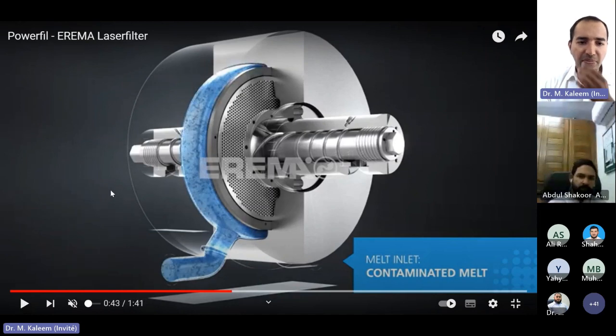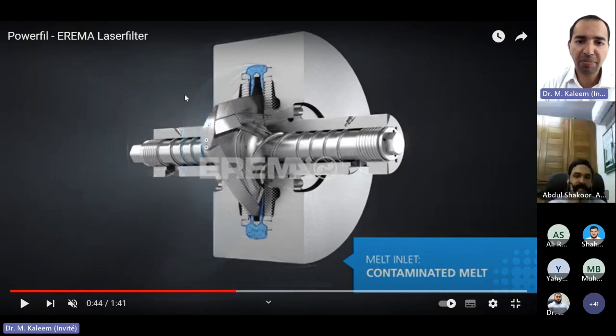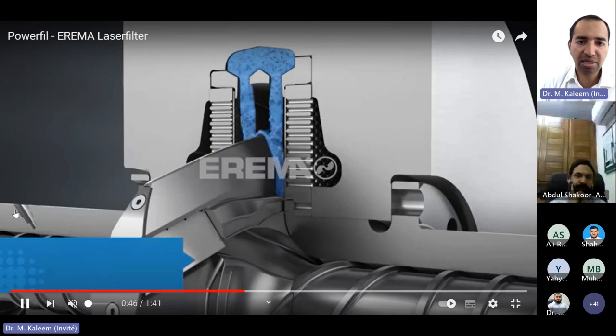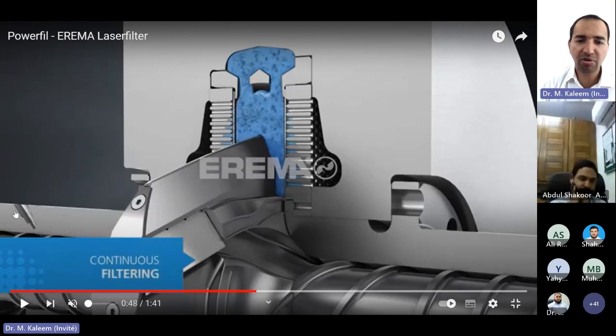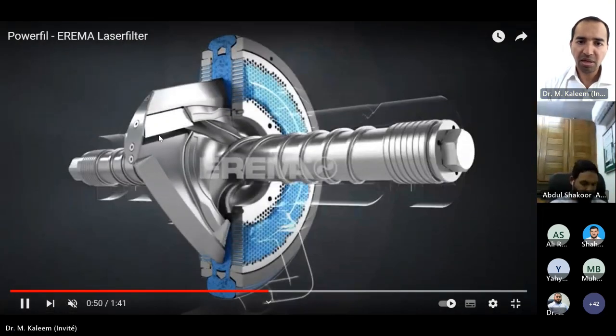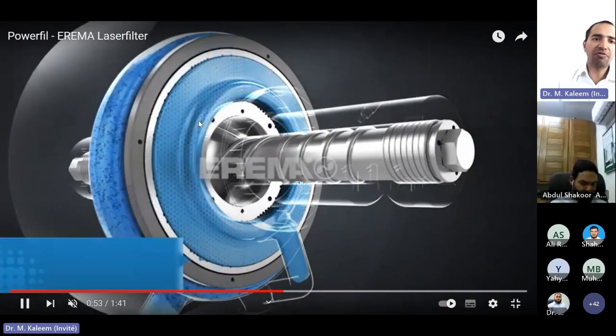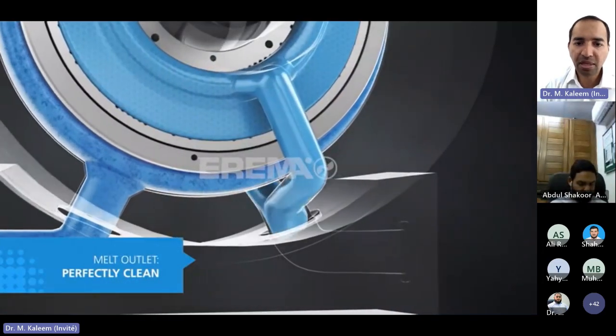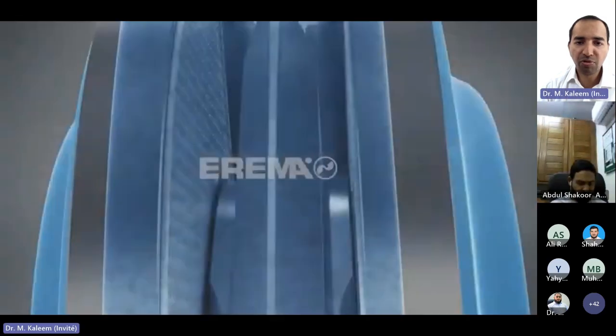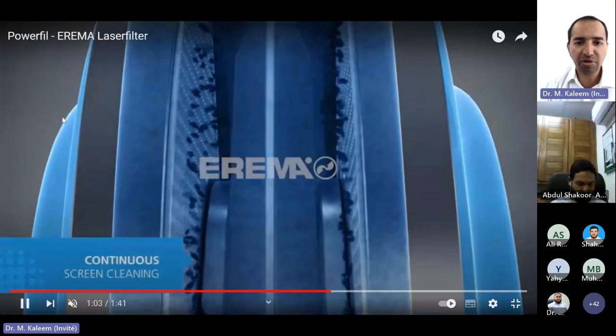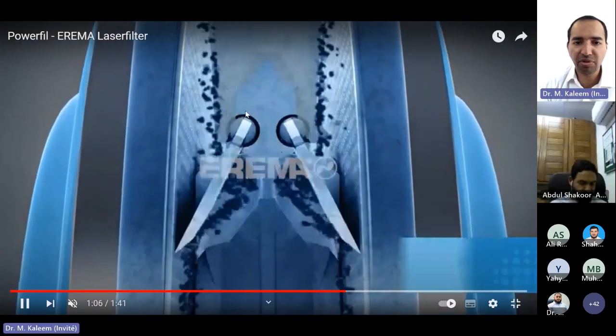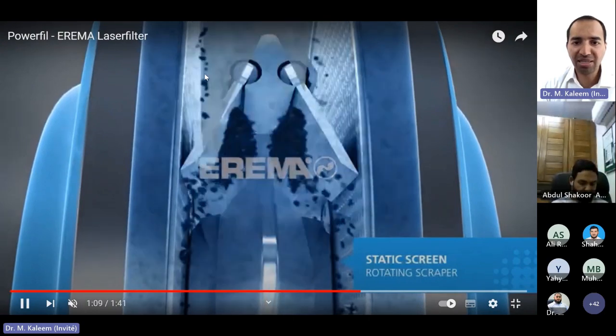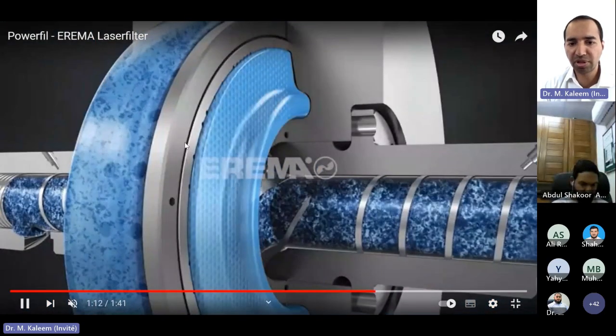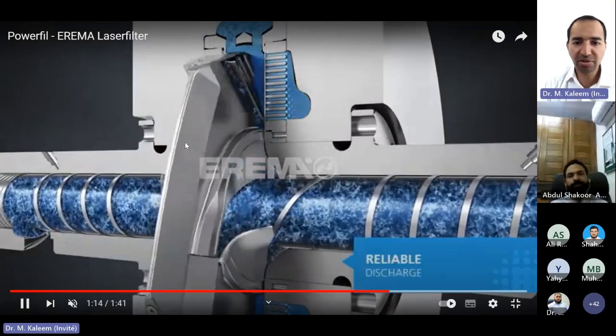So here is the polymer melt with a lot of contamination inside, and this is the filtration system. Like I said, if the material feedstock has a high contamination level, you have to remove the impurities continuously. This is a laser filter from Erema that continuously removes the impurities. Here is the feedstock melt stream with all the contamination, and this is a blade that continuously removes all the impurities from the polymer melt stream.